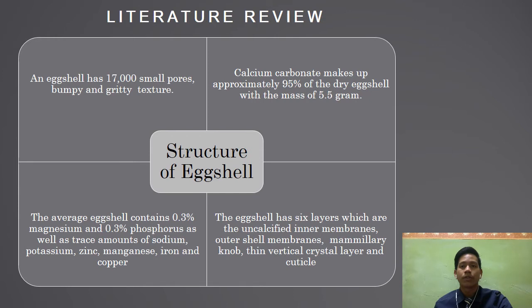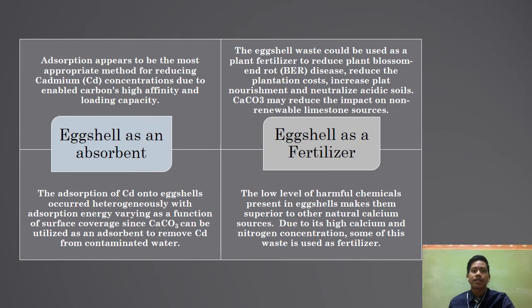Firstly, I would like to talk about the structure of eggshell. An eggshell has 17,000 small pores, bumpy and gritty texture, mostly composed of crystals of calcium carbonate. Calcium carbonate makes up approximately about 95% of the dry eggshell with a mass of 5.5 gram. The average eggshell contains about 0.3% of magnesium and 0.3% of phosphorus, as well as trace amounts of sodium, potassium, zinc, manganese, iron, and copper. The eggshell has 6 layers, which are the uncalcified inner membranes, outer shell membranes, mammillary knob, thin vertical crystal layer, and cuticle.